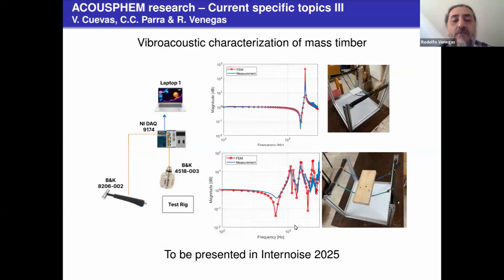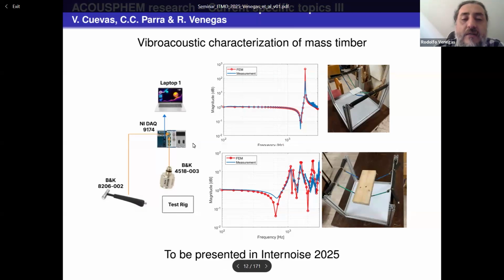Vicente Cuevas is working on vibroacoustic characterization of mass timber. So the idea is to implement a complete system for the vibroacoustic properties or anisotropic properties of complex materials like wood. In this example, this is a plate of aluminium, which is isotropic, and can be modeled as an isotropic material, and the comparison between FEM and measurements where we consider normalized transfer functions is very good. And with a transversely isotropic model, we get a relatively good agreement, but it can be improved for the case of wood. This is a radiata pine sample. Also, this is to be presented in Internoise.